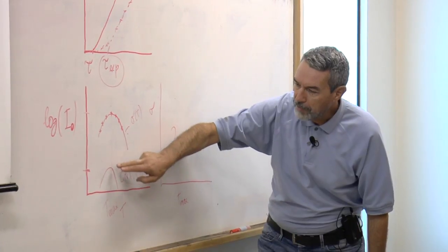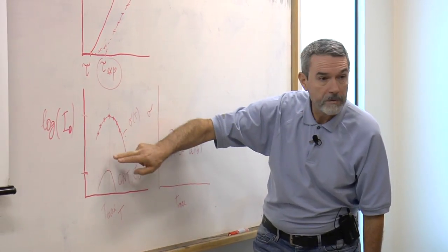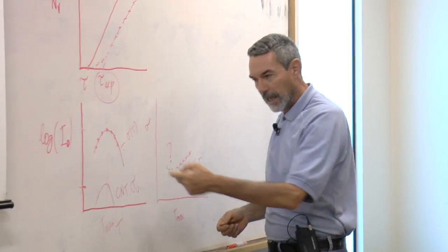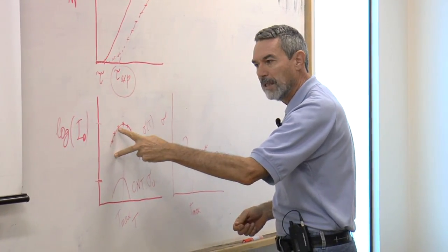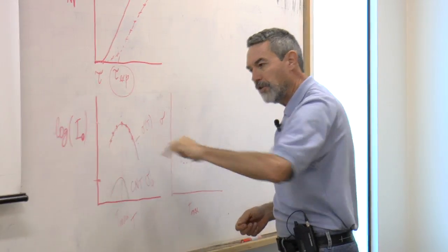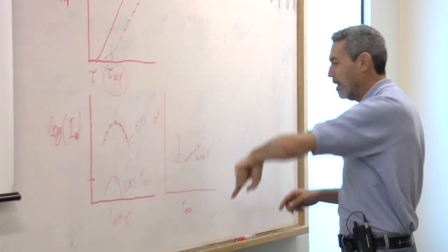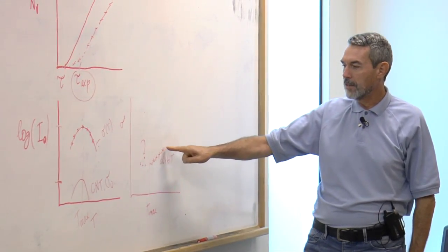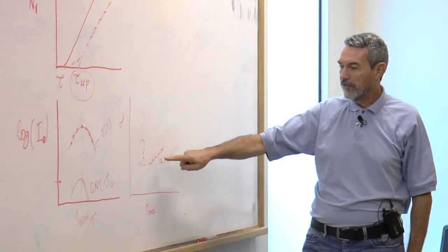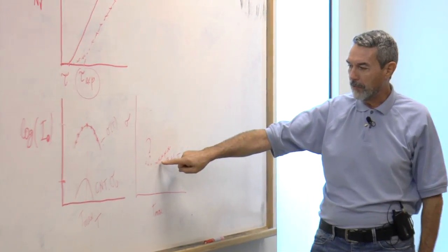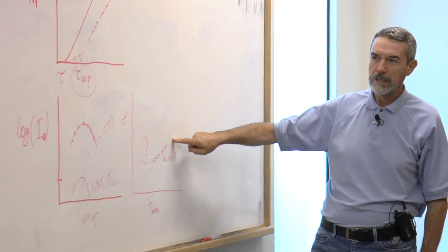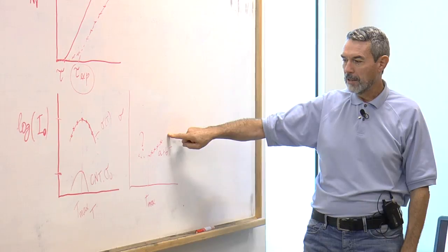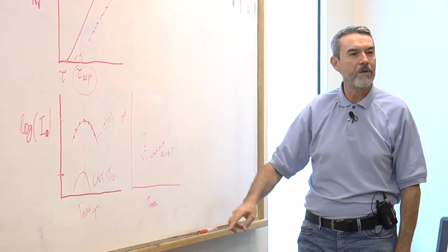It describes the position of the maximum, but not the magnitudes. Now I force fit. I calculate the value of sigma to get agreement with each data point. And the resulting plot is this. Very nice linear variation, so sigma increases with temperature, as the molecular dynamics simulations indicated, but then it decreases below Tmax.